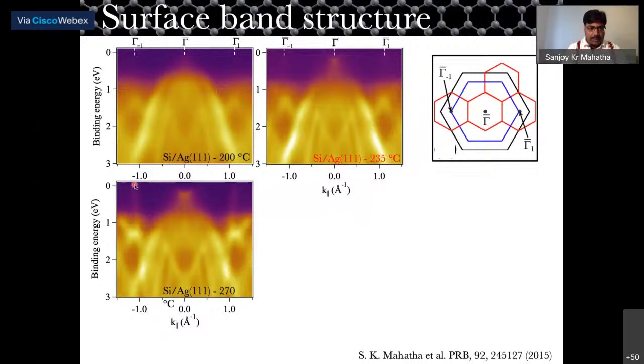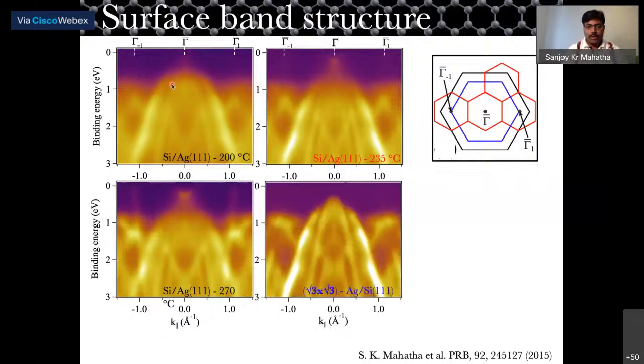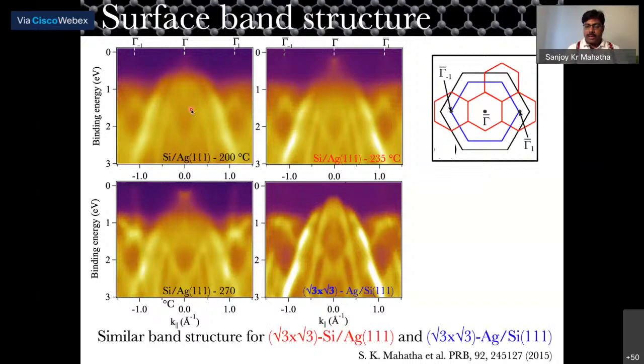And at 270, we see clear indication from silver. These are the silver bands, but at lower temperature, there are no silver bands. So this growth can be compared. And then we also grew this √3 by √3 silver on top of silicon, the reverse system. Then one can see that the band structure is pretty similar. They are both the same. And from here, we said that, okay, this is basically the same system.